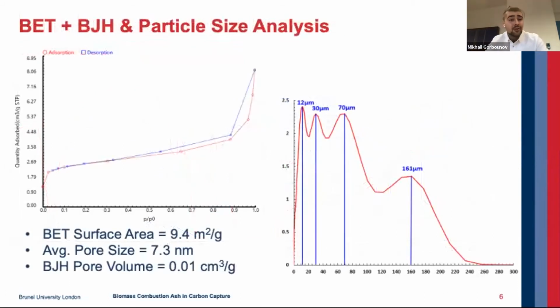Moving on to nitrogen adsorption and desorption and particle size analysis. The typical surface areas of ashes is believed to be in the region of 2 to 6 square meters per gram, with coal ashes being on the lower limit and biomass ashes being a little higher. However, our investigated fly ash appears to be much more porous than the others reported in the literature. The specific surface area of the fly ash is approximately 9.4 square meters per gram.